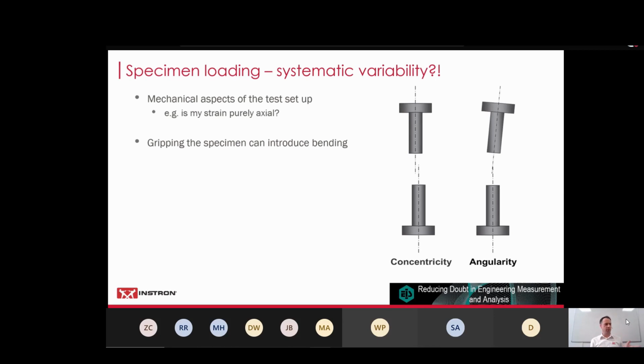And this is perhaps something some of you have encountered and talked about, and is the idea of gripping and getting accurate alignment. Now, if you clamp your specimen, clamp your test piece, and it's nicely aligned, everything's good. If you clamp it and one end has ended up offset or twisted, then you're now going to introduce some bending into your test piece. As you bend a specimen, obviously one side is pulled into tension, the other pushed into compression. So now the surface ligaments aren't going to be seeing the same as the average strain that you're intending to put on.